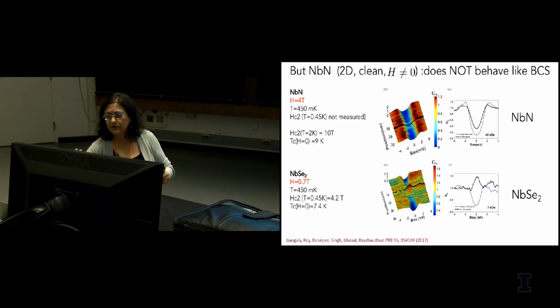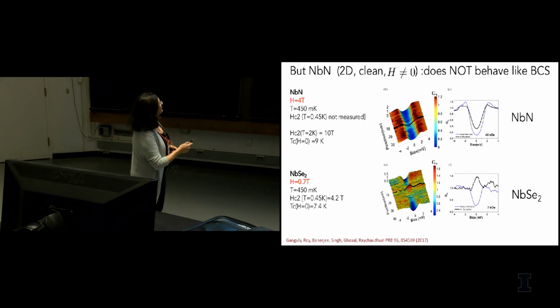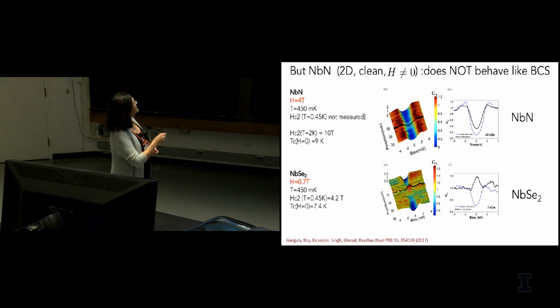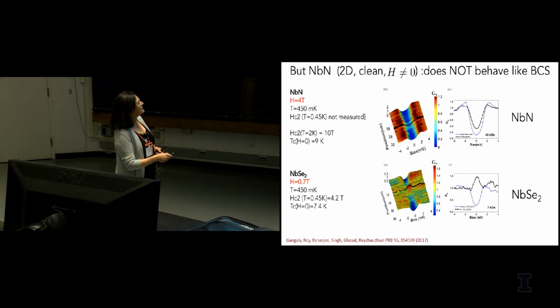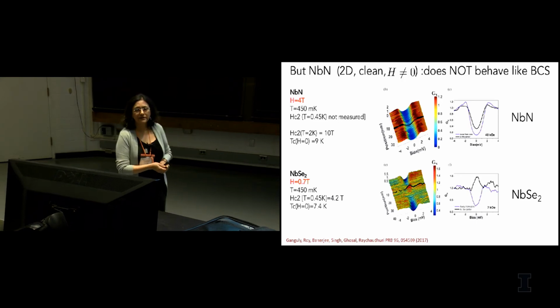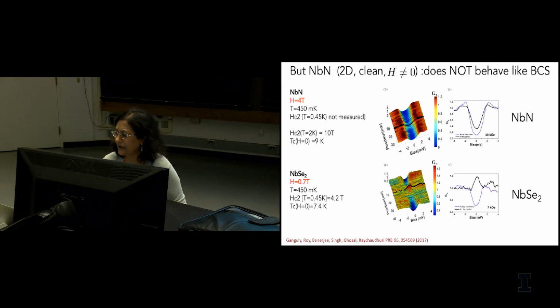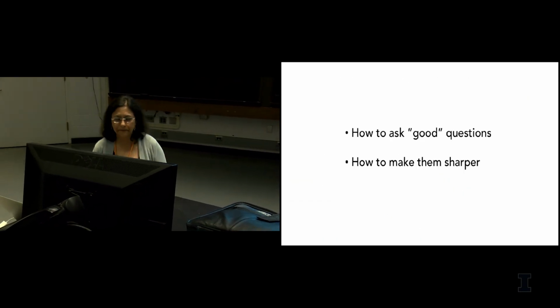And so it's a good BCS superconductor, but when they apply a magnetic field, that same material shows a density of states which is a suppression at the vortex core, rather than another system like niobium diselenide, which has a metallic core. So these experiments are just beginning, and I think we'll see much more on that.